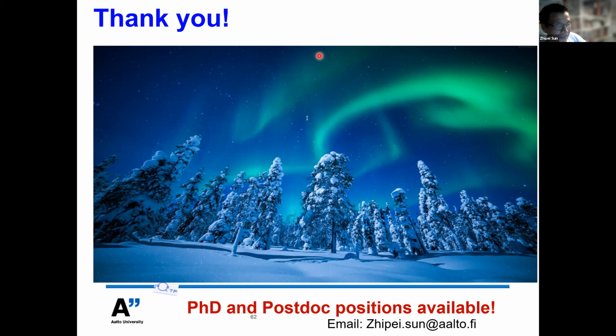In our case, we tried different strategies to remove the photoluminescence resonance. One easy way is, if you look at the second harmonic generation measurement I mentioned, if we use polarized second harmonic generation, the generated light is always polarization dependent. But for the photoluminescence resonance, the PL emission doesn't have any polarization preference, because this is a spontaneous process. In this way, we could easily remove the contributions from the photoluminescence process.